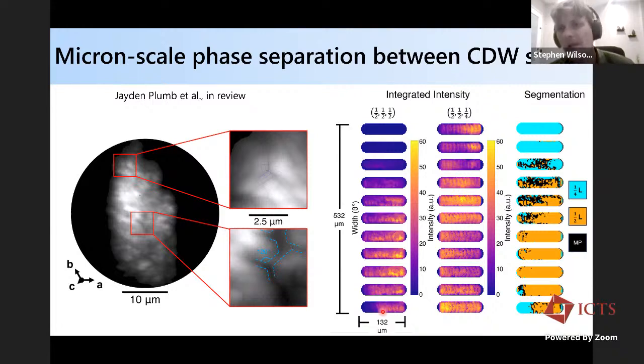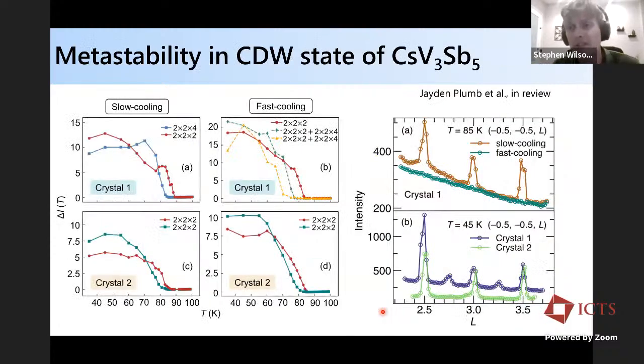And so what this is implying is that you have these competing charge density wave phases, and they phase separate locally in the system. And this is consistent with this thermal hysteresis and the metastability in the material. And so we can look at this a number of different ways.